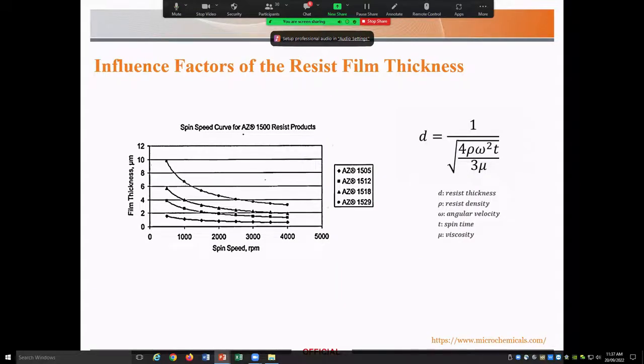The thickness of the film is affected by the viscosity of the photoresist as well as the spin speed and time of spinning. Usually with conventional spinning speeds, like 3,000 or 4,000 rpm, the final film thickness is completed. And then further thinning happens during the spinning and the subsequent soft baking process, with solvent evaporation.